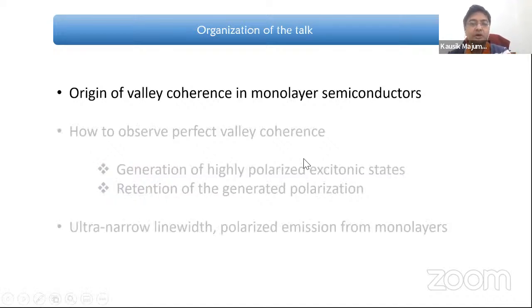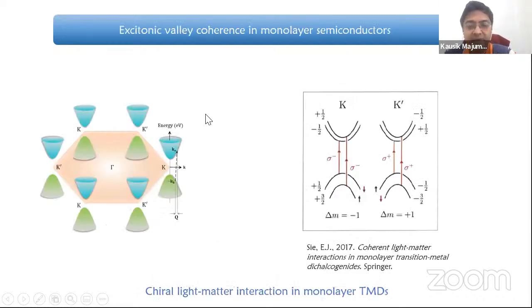All right. So let's first see what we mean by valley coherence in monolayer TMDs. In TMDs, the monolayer semiconductors, we break the inversion symmetry, and we have a chiral light-matter interaction. In particular, in the Brillouin zone, you have the inequivalent K and K prime valleys. Because you have to conserve the angular momentum in any process, if the K valley, for example, absorbs sigma minus polarized light, then the K prime valley would absorb sigma plus polarized light.